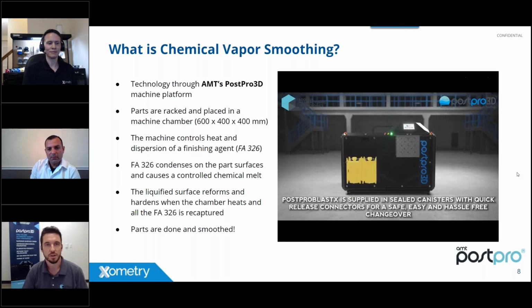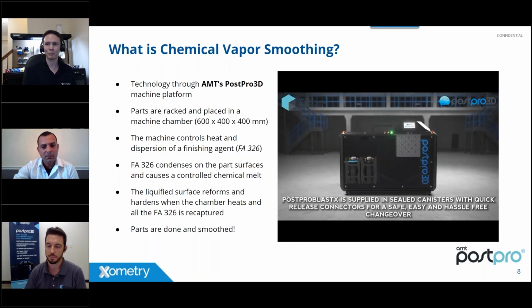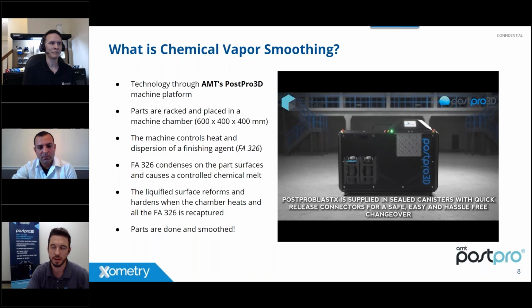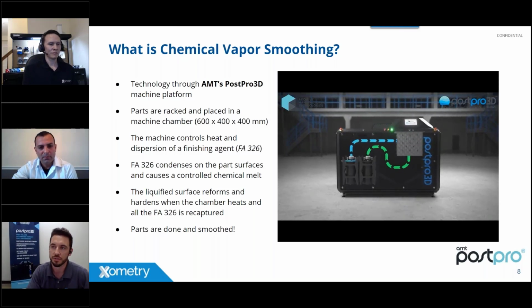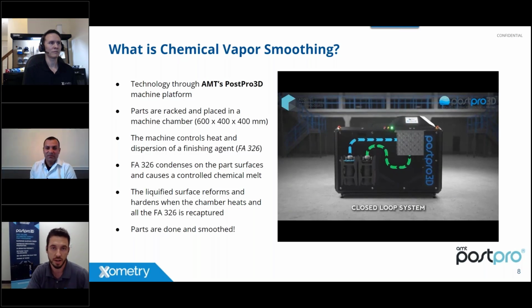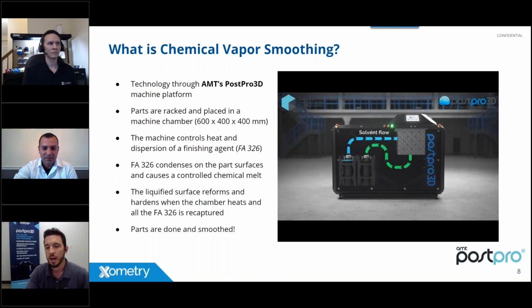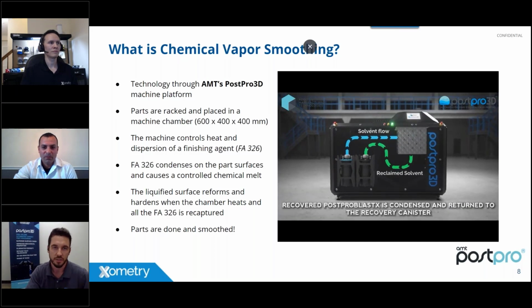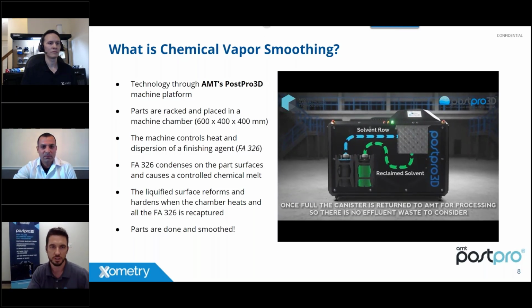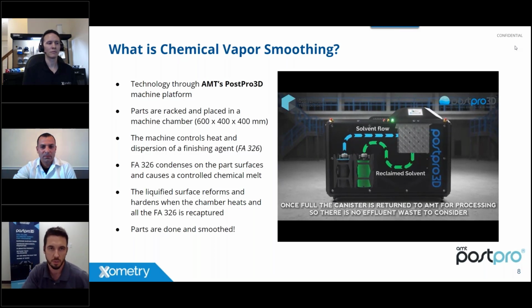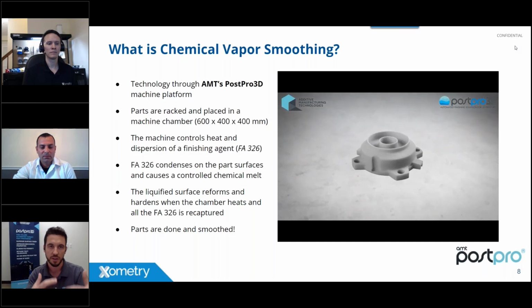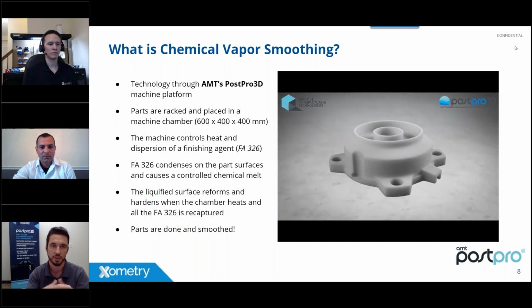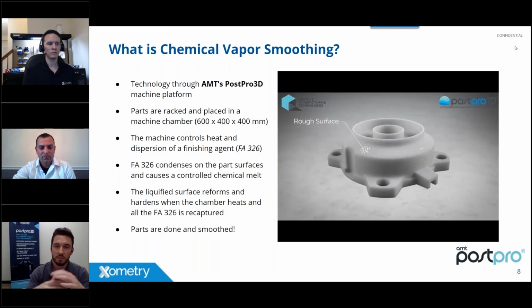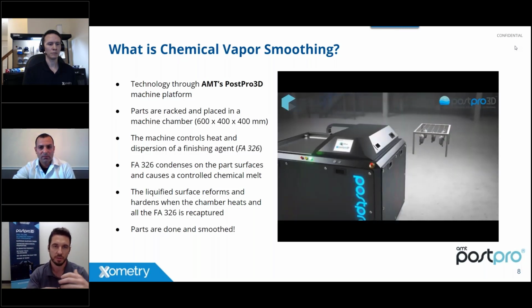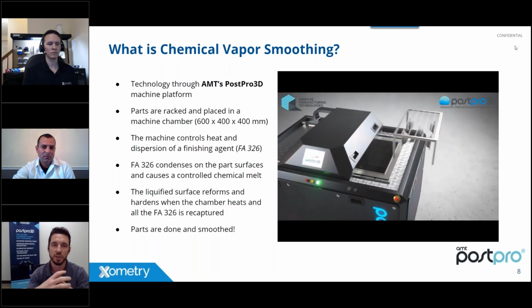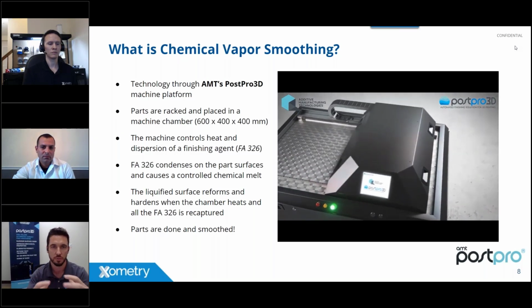Yeah, thank you, Greg. Thank you for the intro and for painting a picture of what we experience traditionally when it comes to post-processing. As you mentioned, a lot of it is very labor intensive and limiting, whether it's the process or the media size for tumbling, for example. But there's a lot going on on the surface of a printed part. The technology is great, but when you start really peeling back the layers of what's involved with printing, there's a lot that we can fix and improve upon on the finish and surface of these parts. So vapor smoothing is taking that final step of fixing that surface and removing blemishes, the crack initiation sites, the roughness and everything.